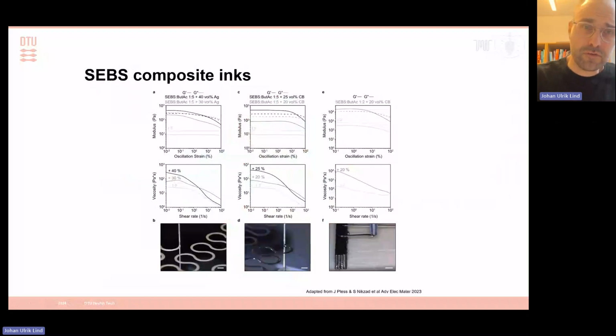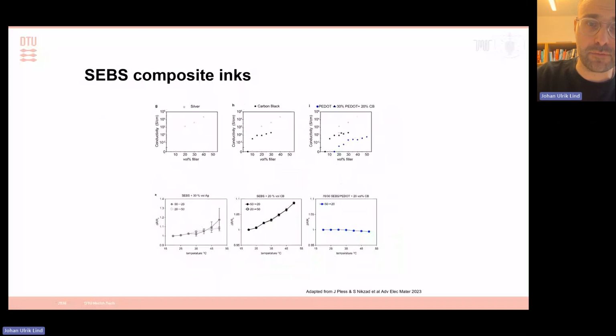But we have also focused a lot on SEBS. SEBS is another thermoplastic elastomer. But as compared to the polyurethanes that we used before, we can dissolve this in much more benign solvents. So we still apply this nail polish rheology, you could say, to print thin films, but we can also print freestanding features by going into a more high viscosity domain. So just a couple of examples. We're exploring those for different types of sensing.